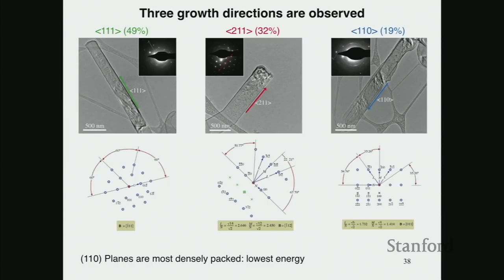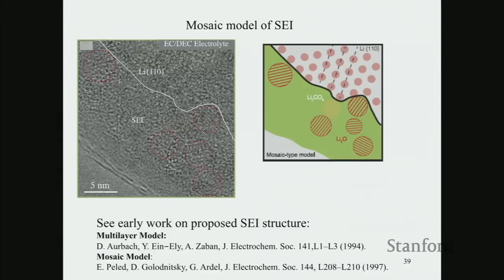We discovered that along the 111 direction, 50% of the dendrites like to grow. Along 211, 30%, and 110, 20%. There is a reason why it is more along certain directions, because the sidewall surface tends to terminate with a particular crystalline surface, 110. That's the lowest energy surface. That can actually explain this behavior.